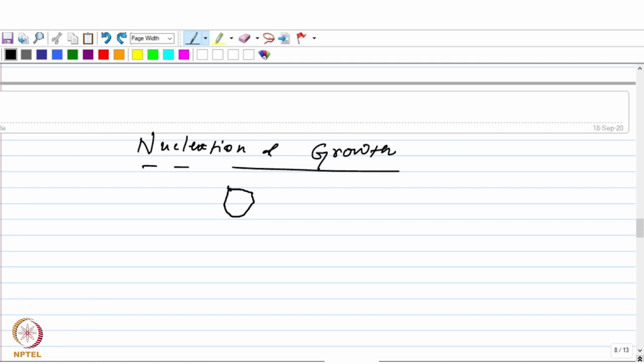So this nucleus which has formed is strain free, but the rest of the material is still strained. So this has to grow and consume the rest of the strained material for it to be recrystallized, right? So this nucleus has to now grow, and the growth in this case occurs by grain boundary migration, so that it can consume the rest of the strained material, the rest of the strained grains.